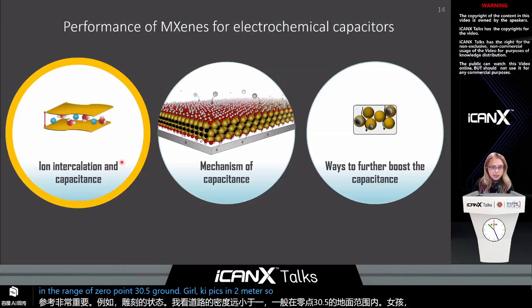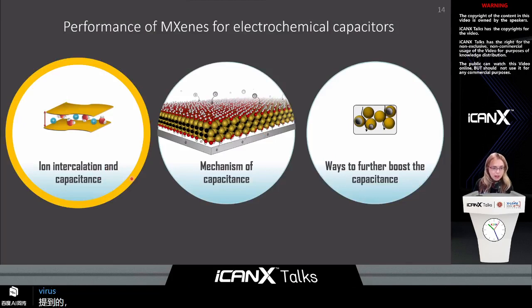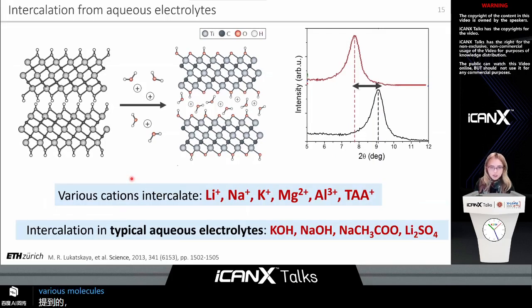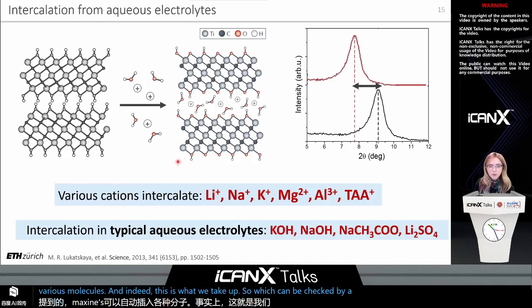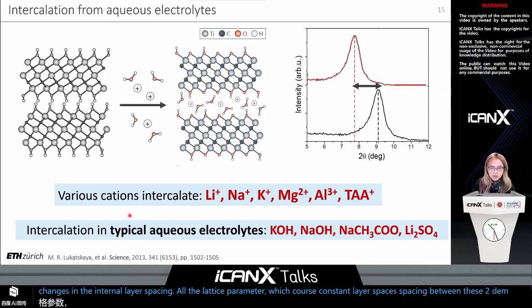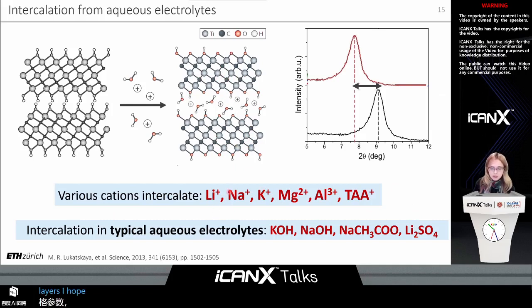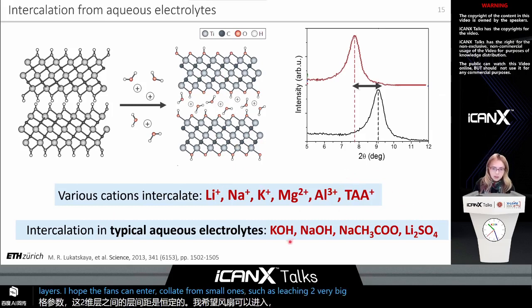So as I mentioned, MXenes can be spontaneously intercalated by various cations and molecules. And indeed, this is what we typically observe, which can be checked by doing X-ray diffraction and looking at the changes in the interlayer spacing, or the lattice parameter, which corresponds to interlayer spacing between these two-dimensional layers. A lot of cations can intercalate, from small ones such as lithium to very big ones such as tetraalkyl ammonium.